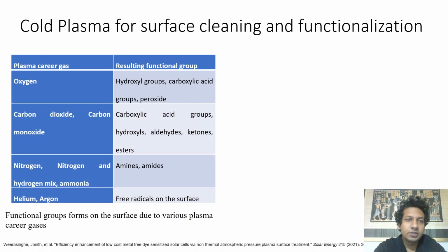The well-known industrial usage of cold plasma is its capacity to treat surfaces such as polymers, ceramics, composites, metal and metal alloys. Plasma treatment lacks the limitations of other functionalization techniques such as chemical and thermal treatments. These techniques are less efficient or produce byproducts which are toxic to humans and the environment. Glow discharge and radiofrequency plasma treatments can activate, provide anchoring sites, functionalize certain functional groups, and improve interfacial bonds. During the plasma process, chemical functional groups or free radicals on the surface induce cross-linking or surface grafting. Various surface activation processes due to different plasma carrier gases are summarized in the table.